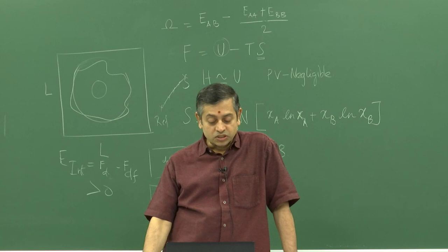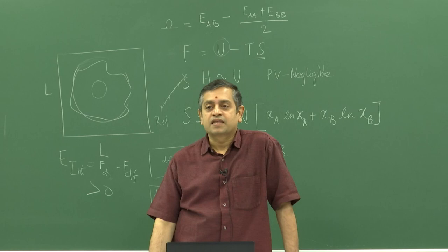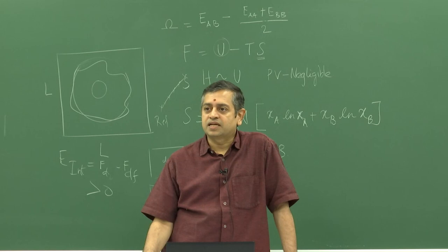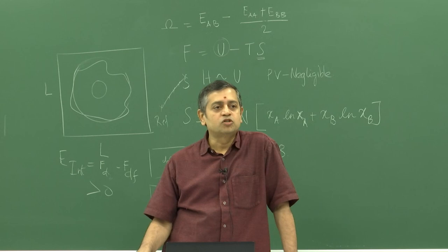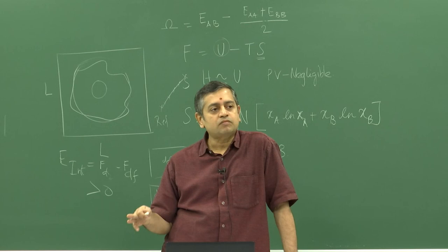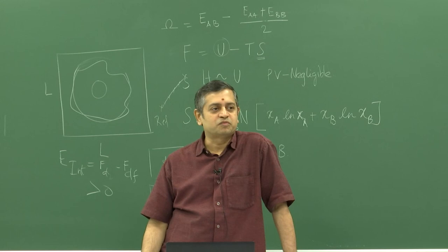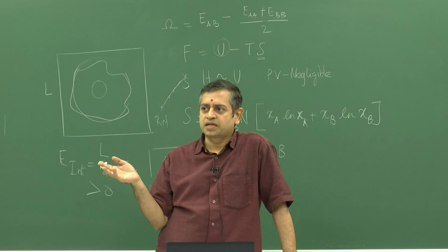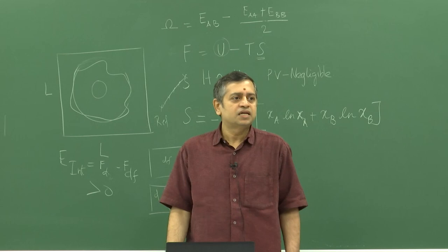The reason why we got interested is to calculate stacking fault energy at non-zero temperatures. In fact, we wanted it as a function of composition too, because in the copper-aluminum system, with increasing amounts of aluminum, the stacking fault energy drops from 40 millijoules per meter squared to almost 0 by about 12, 13 atomic percent. That is why there is a phase transformation. There is a two-phase region that comes up with an HCP structure at lower temperatures. That is because the stacking fault energy has become negative, which almost guarantees a phase transformation. Instead of being FCC, the system would prefer to be HCP and rich in aluminum. That is also seen in cases where it has not phase separated: if you have a stacking fault, aluminum atoms prefer to sit next to it because they somehow prefer the HCP arrangement when you have copper and aluminum.